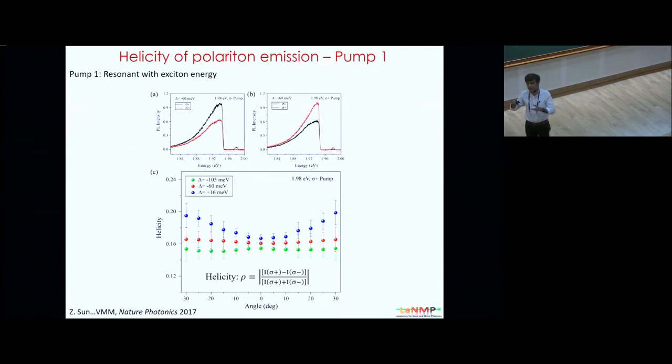The TE-TM splitting also destroys valley polarization inside these systems, and hence at larger values of k, you're going to get lesser and lesser of this helicity being restored. So especially for the large detuned cavity, which is very photon-like, this TE-TM splitting actually dominates over the other effect, and hence we lose some of the helicity. Nevertheless, you're getting about 16 to 20% helicity inside these samples, which is comparable to what happens in bare materials.